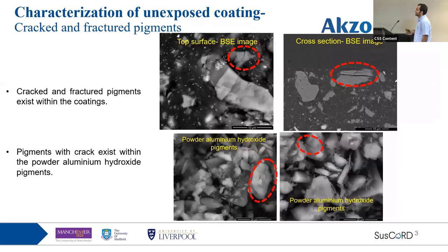Looking again at the unexposed panels, we can see that some of the particles are fractured within these coatings. We can also see cracks within the particles, but these cracks haven't led to fracture of the pigments. The source of these cracks, I think, can be within the pigments themselves. These are images of the raw pigments, and we can see some cracks within the pigments themselves. But also, during the formulation and mixing of these powder coatings, the powders go through different steps and processes, each of which can put some stress and force on the pigments and result in further fracturing or make cracks within them.